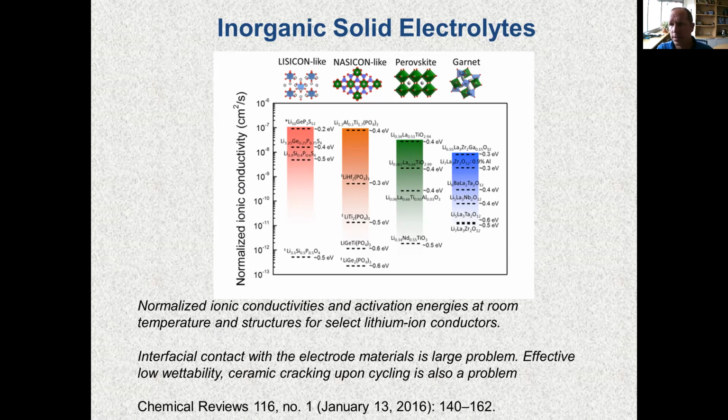However, the biggest problem with these ceramic inorganic solids is they've got poor interfacial contact with the electrode materials. And so basically what you're trying to do is to incorporate a solid inorganic solid into a cell where you have already solid cathode materials, lithium cobalt oxide, and anode materials, graphite. And at the same point, it's very hard to get wettability. So these have a very low effective wettability. It's very hard to make good surface contact between the inorganic ceramics, the LISICON, and the lithium cobalt oxide, especially around the entire particle. If you recall, these cathode particles are basically spherical in nature, and it's very difficult to get the solid inorganic solids down into the pores of the cathode and the anode.